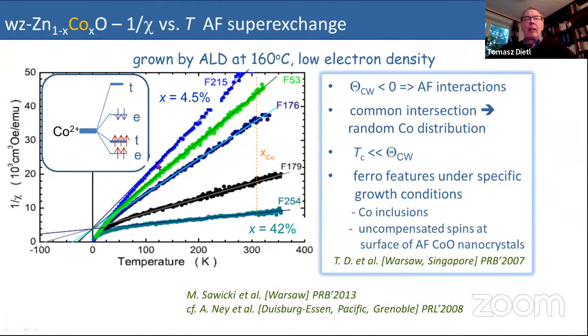We see also that down to very low temperature, actually, we do not see too much ordering. And also, one of the reasons people were so much interested in this material is that under specific growth conditions, you can observe ferromagnetism. And nowadays, I think most people agree, there are cobalt inclusions which account for this ferromagnetism, or, this is more fancy and less popular, uncompensated spins at the surface of antiferromagnetic cobalt oxide nanocrystals are involved here.